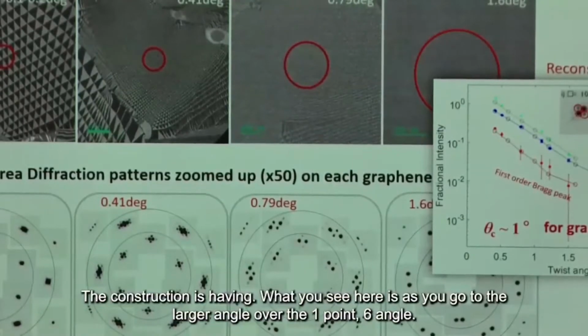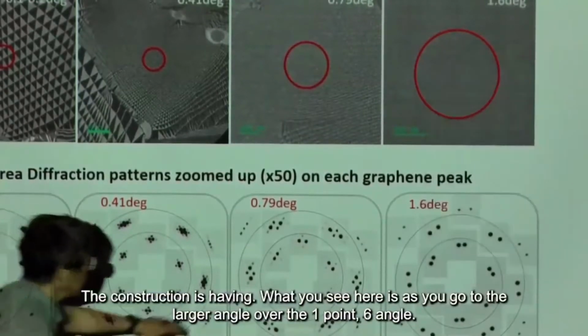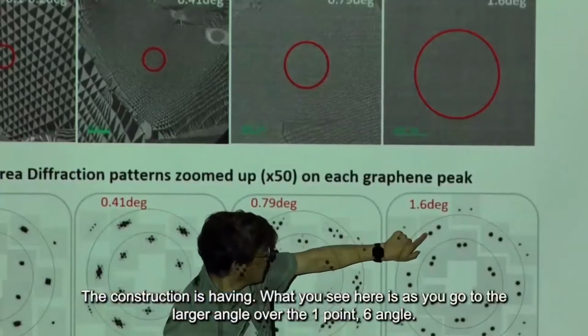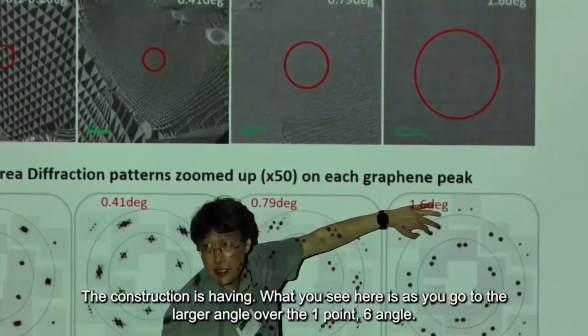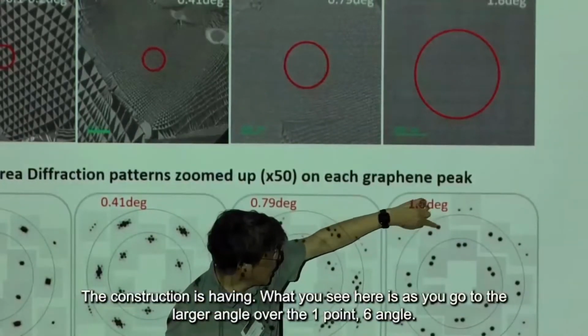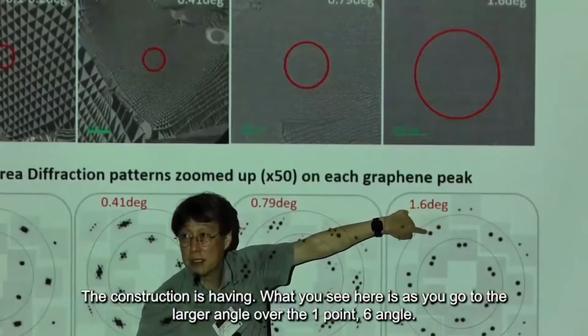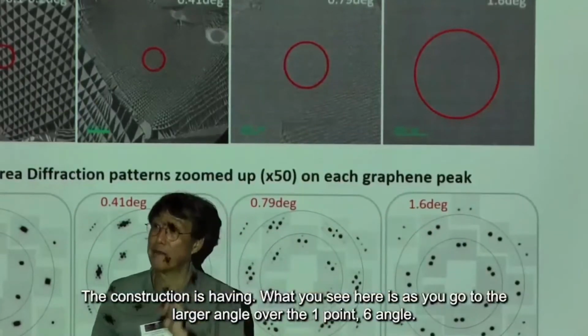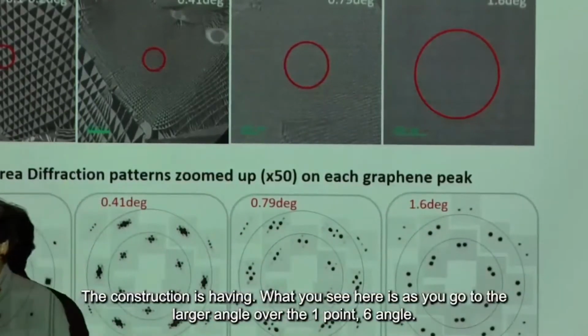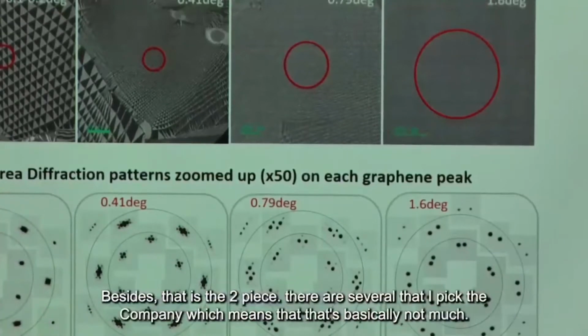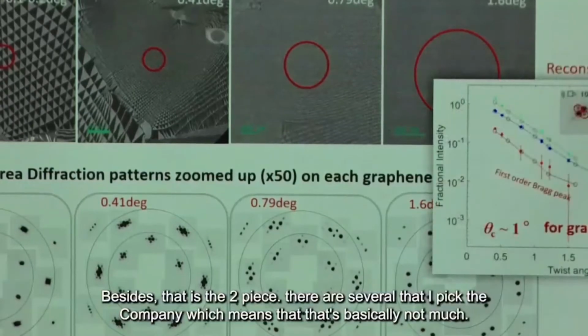Analyzing these multiple peaks, and especially the intensity, tells you how much of the reconstruction is happening. What you see here is that as you go to a larger angle, already 1.6 degrees, besides these two peaks, the satellite peak becomes really, really small, right? Which means that there's basically not much of a reconstruction. Taking the Bragg peak versus satellite peak intensity gives you a good way to tell how much of the reconstruction is happening.